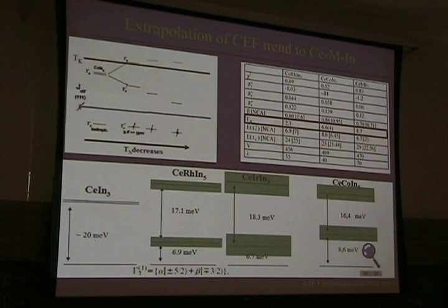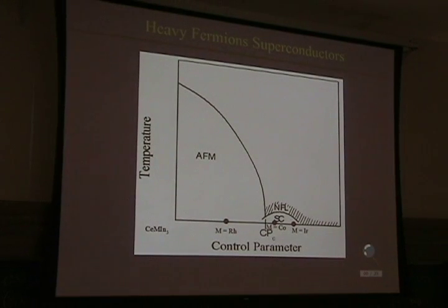So you may take that result and say, well, it has nothing to do with crystal fields. You have rhodium here, right? And your neutron is saying we only increase hybridization, it doesn't mirror the crystal field. And you compensate the f electrons and move here to the cobalt. And if you keep increasing hybridization, you move along that line to iridium, and that's why T_C decreases from iridium when you go to cobalt. So it's just a matter of hybridization.